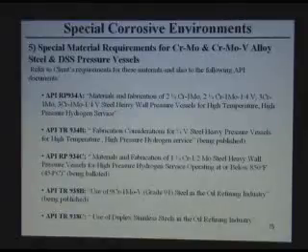When you start using vanadium with the chrome moly, it generates some problems during fabrication, and this document gives some guidelines on what to do during fabrication to avoid cracking. They make a vessel, they make a weld, and they come next day in the morning and find it cracked. So there are some precautions that need to be taken, otherwise you have problems. This document is being developed under balloting now with the API. This is for 1 1/4 chrome heavy wall reactors.